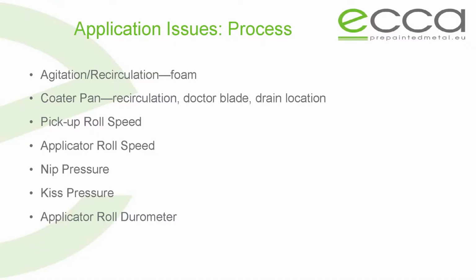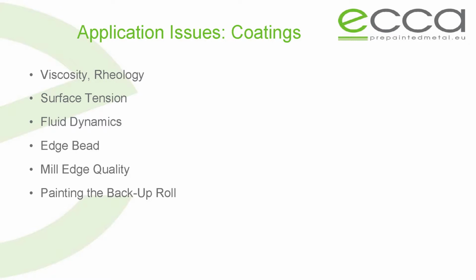So when you're talking about application problems, we are often referring to the issues that are occurring in the coater pan, having to do with either the pickup roll speed, the applicator roll speed, nip pressure, kiss pressure. You've heard all these terms before. The durometer of the applicator. Of course, the quality of the metal. If you've got a bad edge and it tears up the roll, now you're going to have some blistering problems.